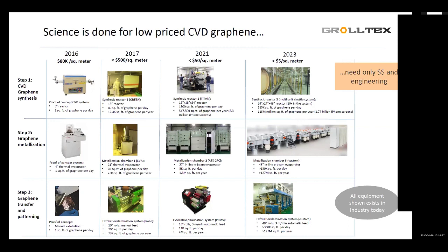So what you're looking at here are the three basic steps it takes for us to make graphene. Step one on the top, of course, is CVD graphene synthesis. CVD, again, very well understood process, been used for decades. Step two, this is where our patented secret sauce kicks in. We metallize that graphene on copper. And the reason we do that is this nanometric layer of, in this case, nickel or cobalt, has a 7 to 10x adhesion rate as compared to the copper. So in other words, the graphene wants to stick to this new nanometric nickel layer more than it wants to stick to the copper, much more. So we put this nanometric metallization on top of the graphene, grab the graphene, pull it away from the copper, and then on a roll-to-roll basis, that copper can go back in the line to make new graphene.